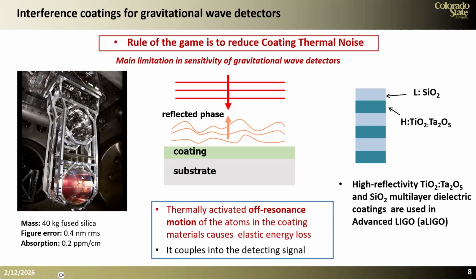And then it's coated with high reflector coatings that now are a combination of silica and a mixture of titanium and tantalum oxide. So the challenge in these coatings is that in the high index material, mainly, we have motion of the atoms that is a thermally activated off-resonant motion that causes elastic energy loss.